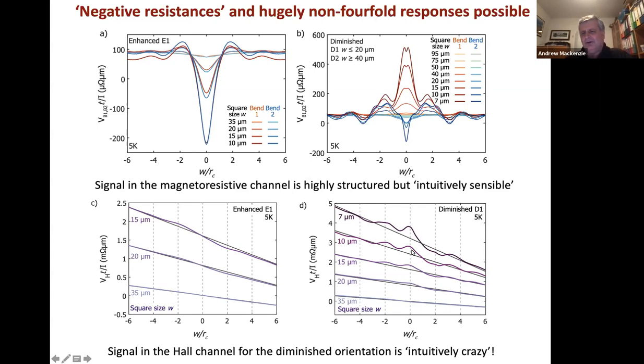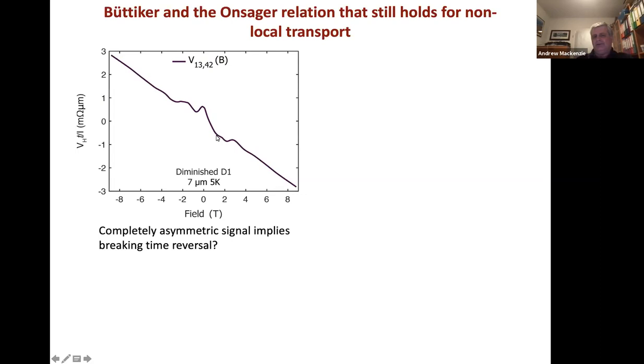Then you go to the diminished orientation, and for a while you wonder if your world has ended, because you see something completely nonsensical, at least intuitively nonsensical. I'll draw that to make that point clear by taking the most extreme example of it. In the diminished orientation, you have an apparently ohmic-like Hall response at high fields, but at low fields where the ballistic physics kicks in, you have a signal which is totally asymmetric. There's no symmetry, either odd or even with field. And the first thing you think is my device is a disaster, and there was a lot of misery on the corridors when this was first seen, I think.